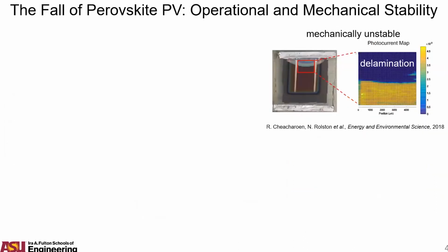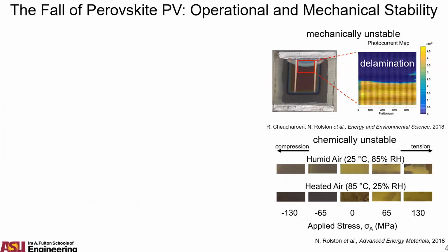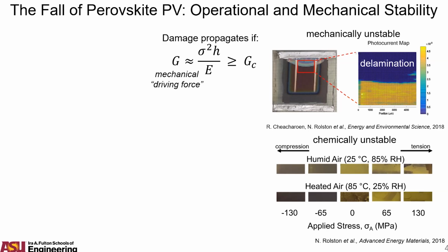However, some of the major challenges: I mentioned these stresses that can develop due to thermal expansion, and that can lead to delamination, and also under environmental conditions such as humidity and high heat, there can also be degradation. Now, fortunately, in space, we won't have to worry about humidity, but heat still becomes a factor. And so we can talk about a driving force for delamination that scales as the square of the film stress. And when that exceeds the material's resistance to fracture, the fracture energy, then you have these damage processes that occur.